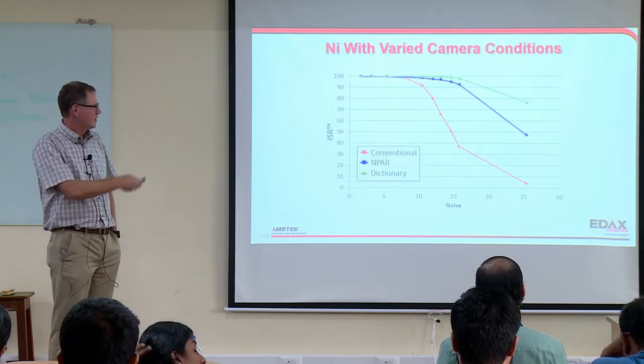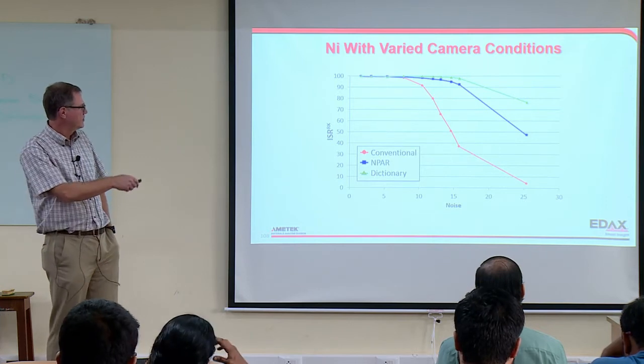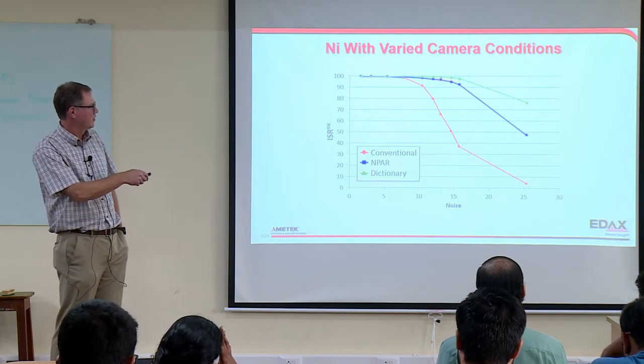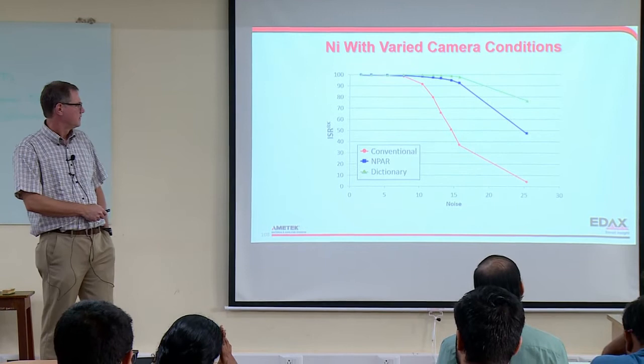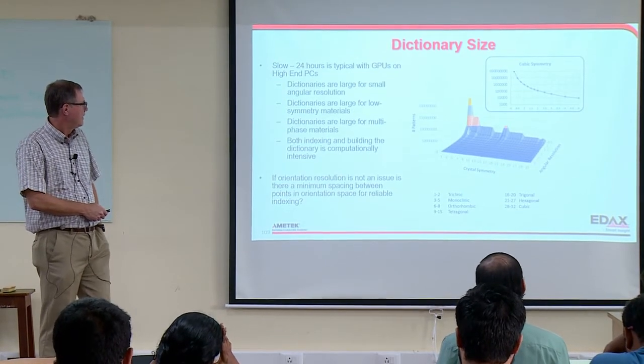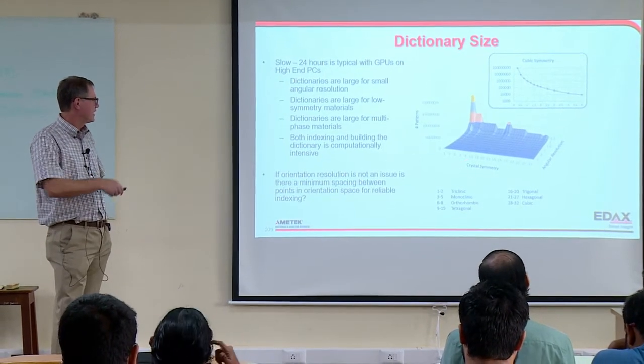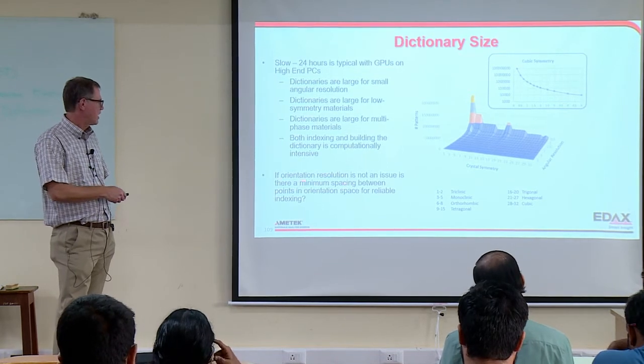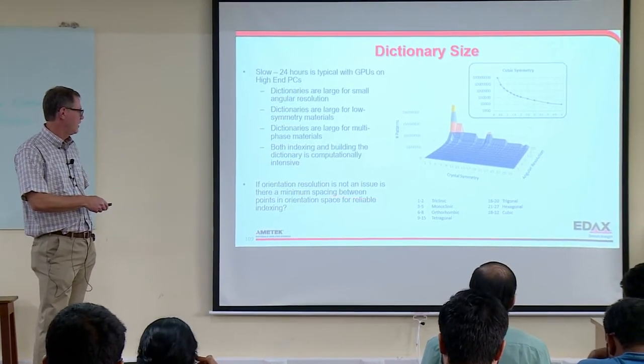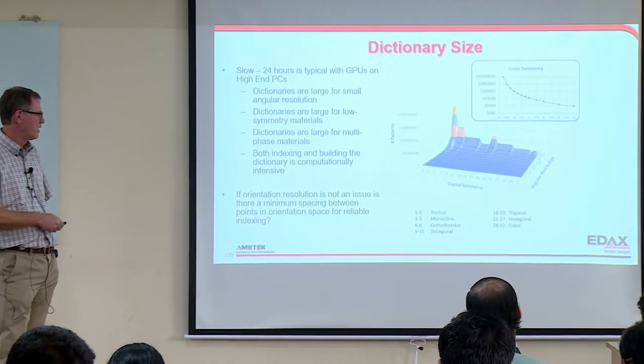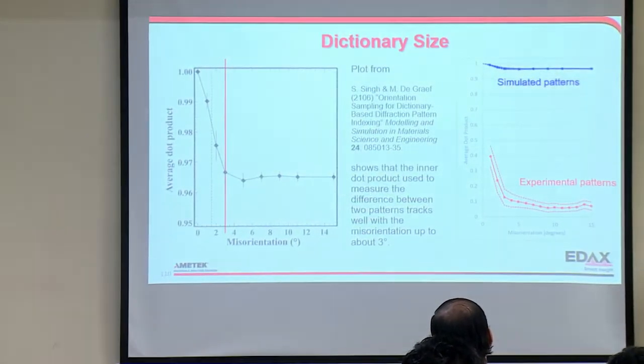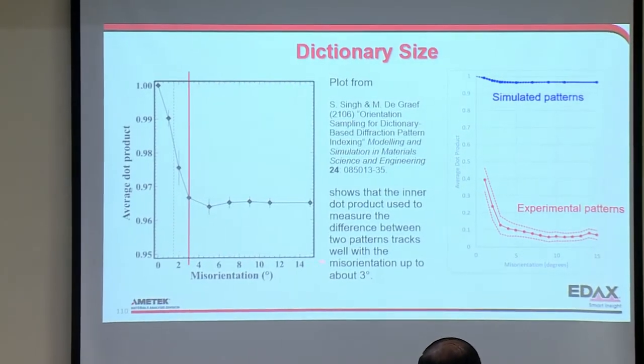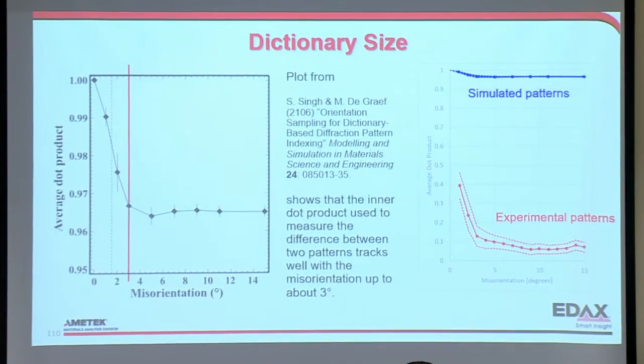But this is the quantitative indexing success rate. You see it does provide an improvement over the NPAR. I mentioned this dictionary size. The question is can we find a resolution where we have a good spacing and we get reliable indexing? So I did a little bit of experimenting with this. This is from the paper on the sampling.